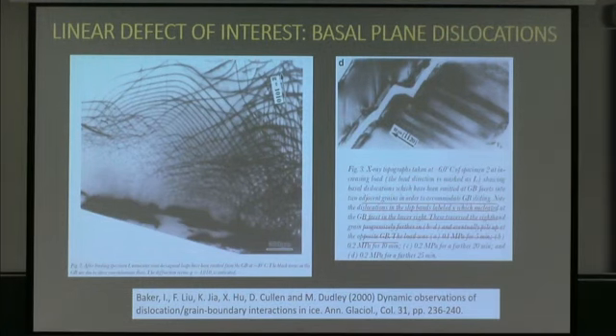Okay, so let's get into dislocations. I got 2 slides and then you're going to be experts. They are linear defects. These are X-ray observations from my colleague Ian Baker at Dartmouth. And what they demonstrate in freshwater ice, these lines are actually dislocation cores. Very well established that they exist. They are very important to ice behavior. And my model quantifies all this behavior in terms of these guys. They support shear deformation on basal planes.